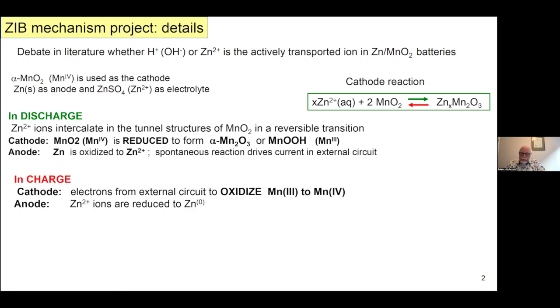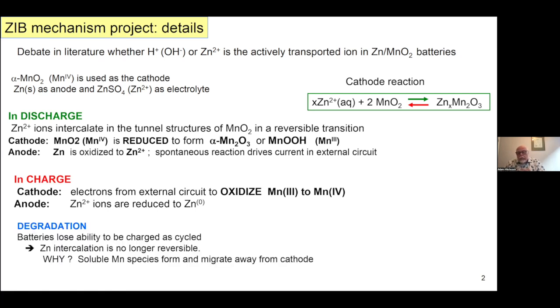And then in the charging mode, we have electrons from the external circuit, which oxidize the manganese 3 back up to manganese 4, and simultaneously some of the zinc 2+ ions are reduced to zinc 0 at the anode. And really, part of the question that we're going to be able to address is how reversible the chemistry is at a given state of use of this battery. Because as you degrade the battery, the number of amp hours that the battery is capable of is reduced.